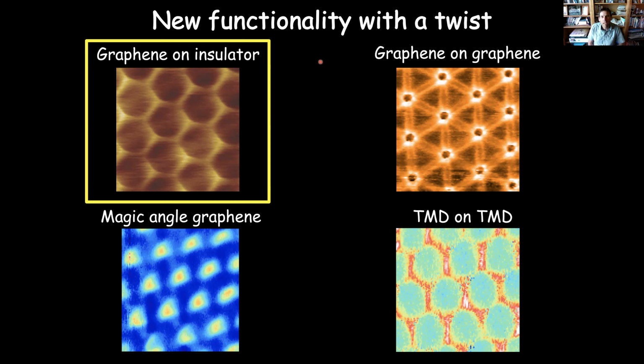A lot of times what we actually end up doing is flipping the entire heterostructure over after making it, and that puts the PC underneath everything. And so then when we're probing on the top with our STM, we're not going to be sensitive to that residue. But which of those two processes we do depends on which heterostructure we're going to make and what order of layers we need to pick up, etc. But we can do either of those to remove the residue.